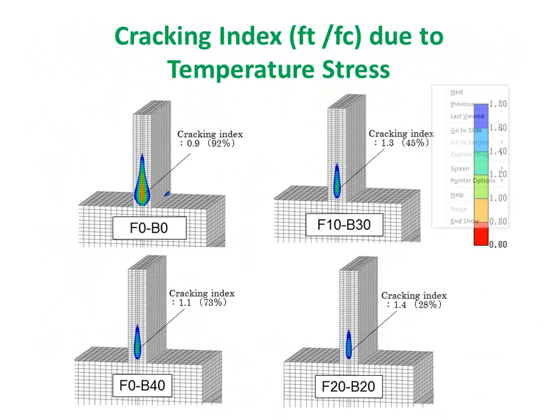And we calculated a cracking index to define these values, Ft divided by Fc. Ft is the tensile strength of the concrete, and Fc is the stress of the concrete caused by the heat stress. If you look at the ordinary Portland cement, the cracking index was 0.9. So it means that there is a 92% possibility of cracking. But if you look at F20-B20, the cracking index is 1.4, so the possibility is very low.